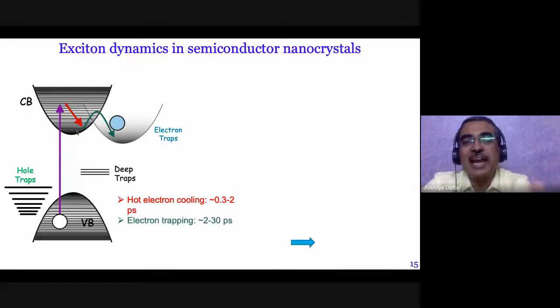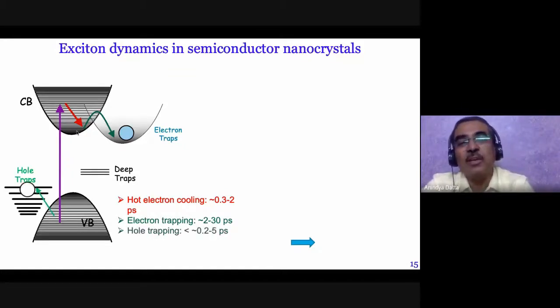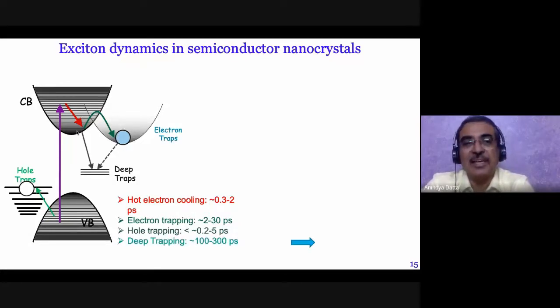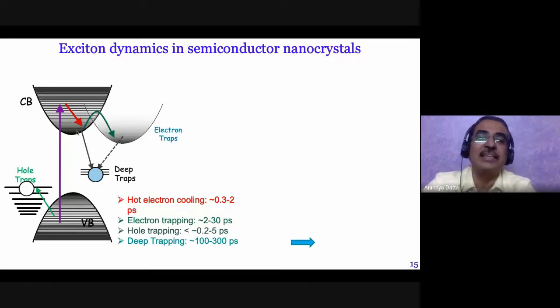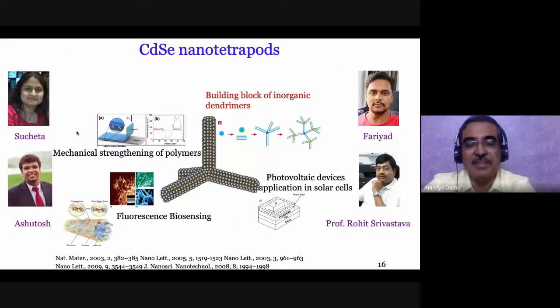And then it can actually be trapped by these defects that are there in the semiconductor nanocrystals. This electron trapping typically takes place in 2 to 30 picosecond time scale. The hole can also be trapped, but it is a faster process. And then you can have deep trapping as well. Deep trap means traps that have energy that is substantially lesser than the energy of the conduction band. So all these phenomena can take place.